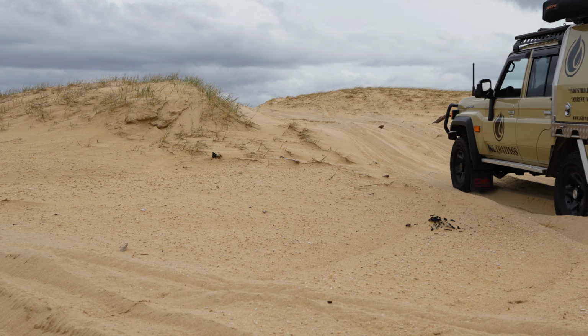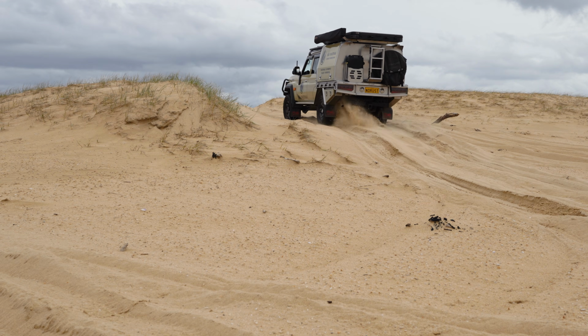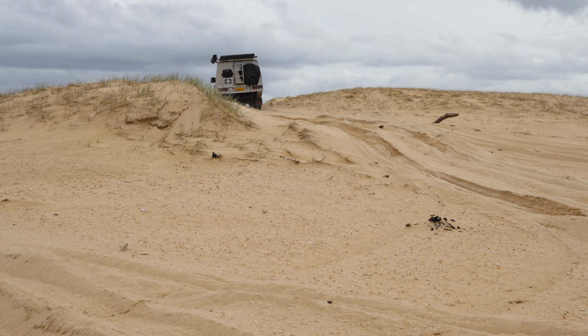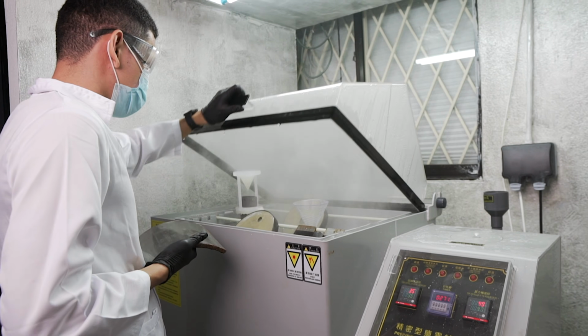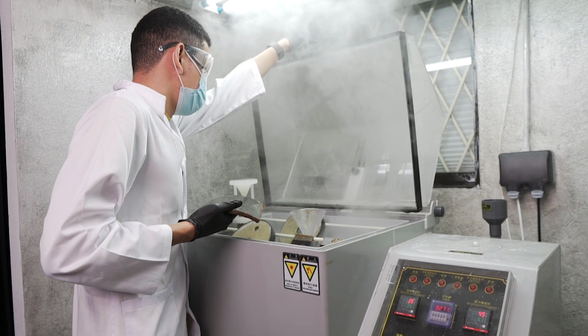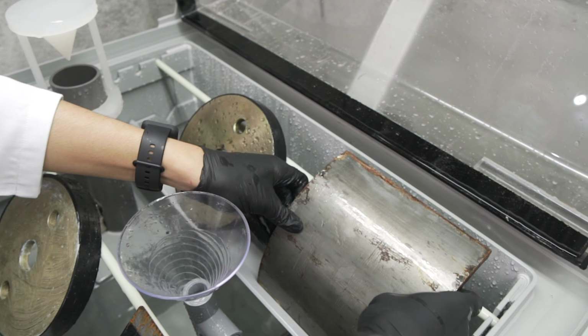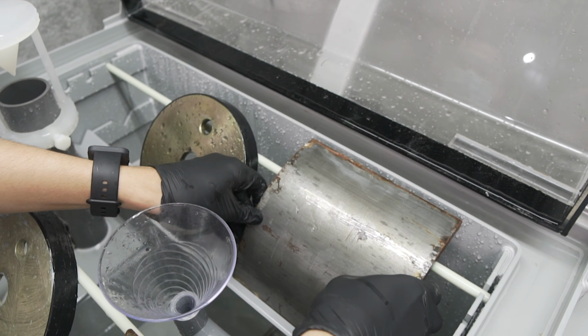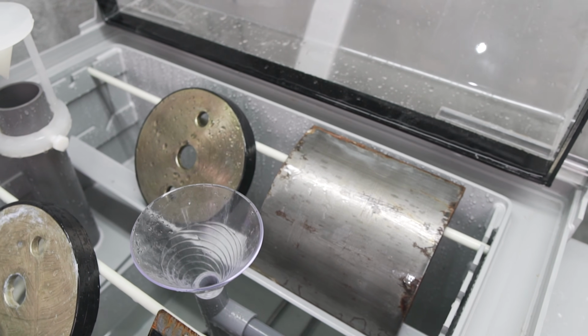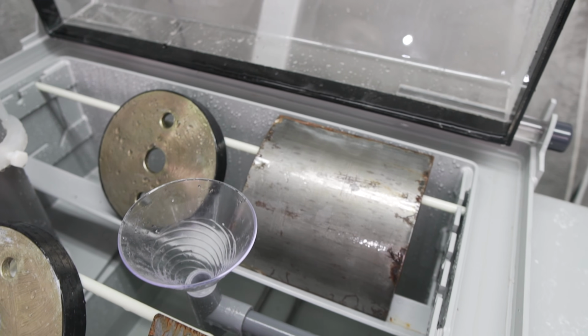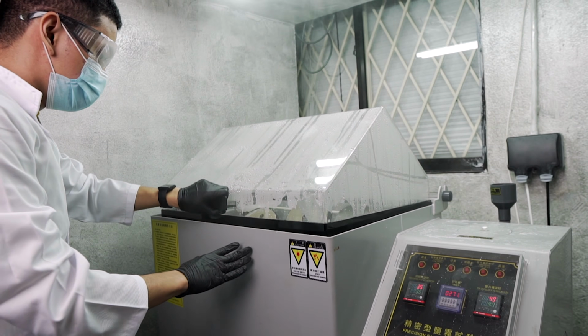This test accelerates corrosion to simulate years of exposure to harsh environments such as beach driving. A coated test sample, for example steel, is placed in an enclosed chamber that is maintained at 35 degrees Celsius, and then it is continuously sprayed with an atomized, dense fog mixture of pure water and 5% salt that is strictly kept at a pH level of 6.5 to 7.2 to create a highly conductive electrolyte environment. This is like a time chamber for rust.